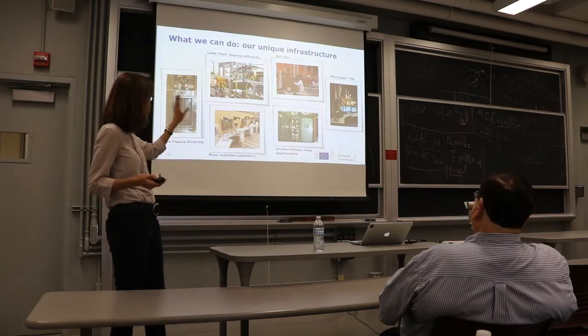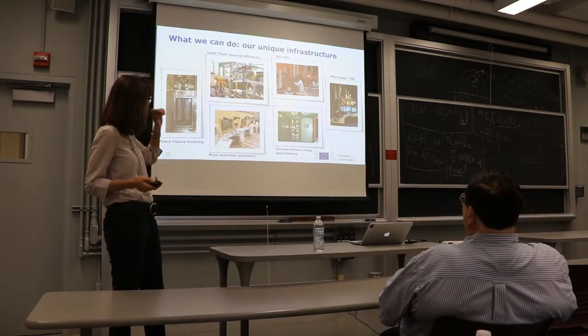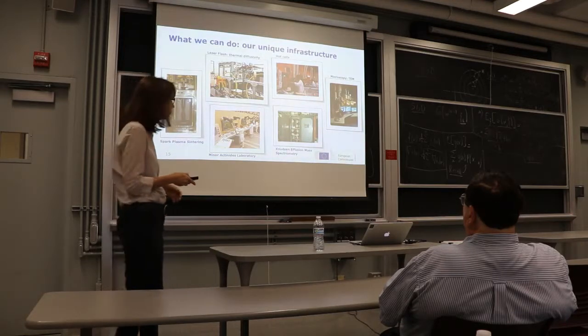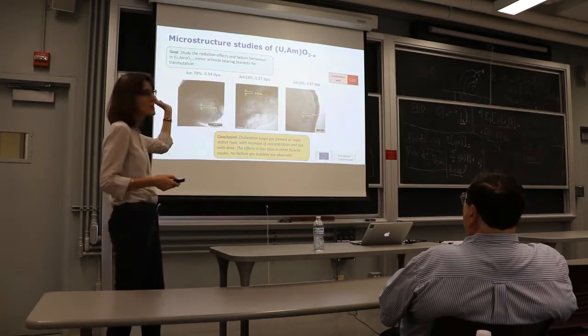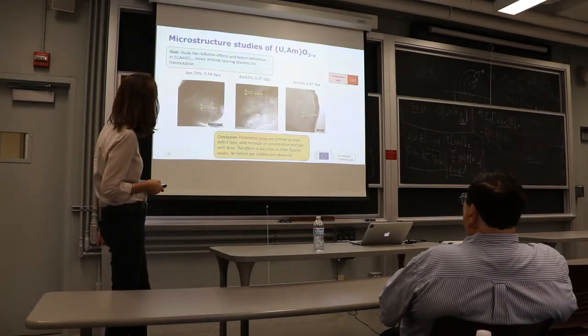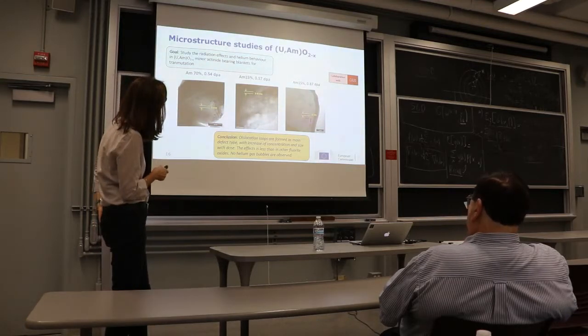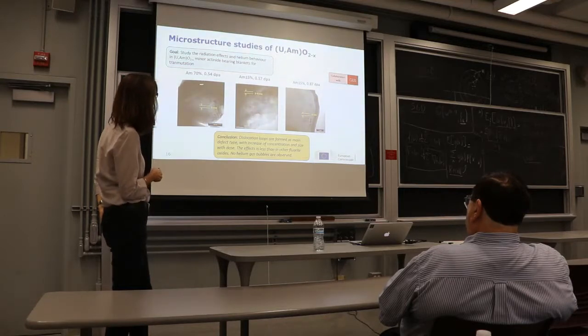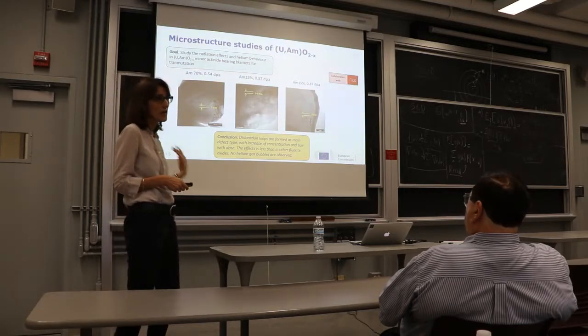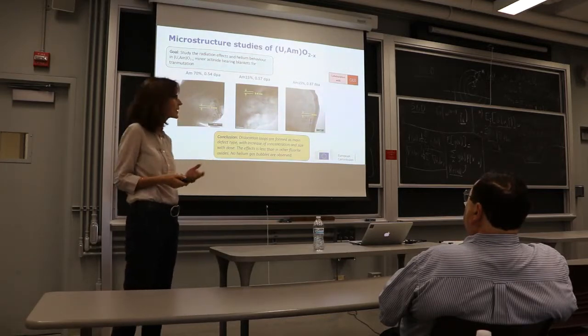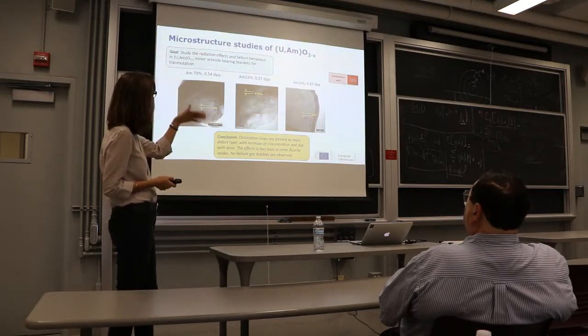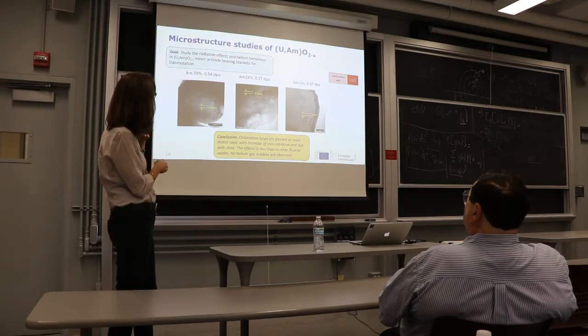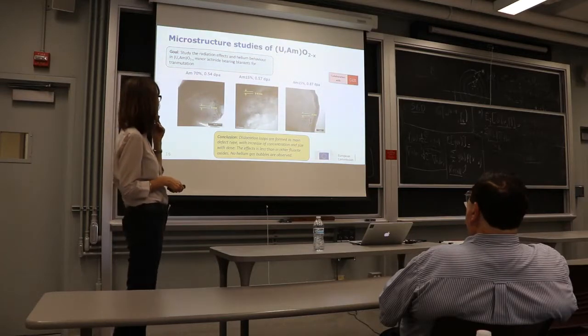So here you see more or less what are our tools that we have available in order to do the fuel characterization. And this is just an example of TEM done on uranium americium fuel with different percentage of americium and different irradiation levels. Here the levels are really quite low, we are less than 1 dpa, so it's really nothing. But the idea was to understand if there is any dependence from the content of americium or the dpa level on this dislocation loops that are formed.